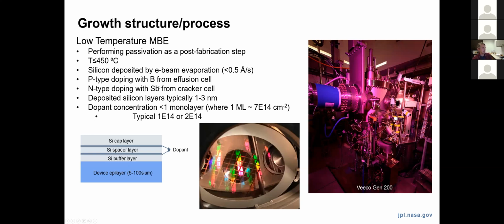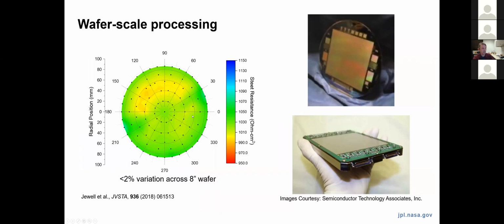And then perform what's essentially evaporation, but it's sort of the fanciest evaporation you can imagine, because of the ultra high vacuum conditions, we have really fine control over the rate of silicon deposition as well as the dopant atoms that are introduced into the lattice. We've done this process in both polarities of silicon. So we use p-type doping with boron for the n-channel devices or the p-type substrates, and then n-type doping from antimony for the other polarity. And again, typically these layers are on the order of just a few nanometers. So that's, again, important to maintain compatibility with that really shallow absorption depth of ultraviolet photons. The dopant concentrations that we get are pretty substantial fractions of the most dopant, essentially, that you can put into the silicon lattice in order to get the most amount of charge for this passivation process.